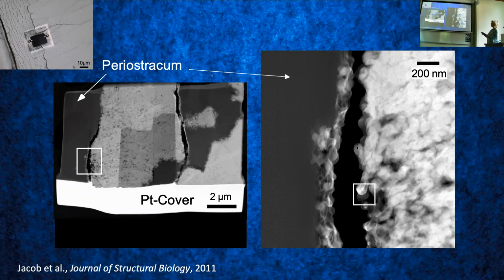So this is the foil we took out from here. This is the outer organic layer of the shell. This is the platinum cover. And you can see from the scale bar how small this foil is. That's about 15 microns by about 10 microns or so, 150 nanometers in thickness in some areas. While we were cutting, it was bending a little bit. Therefore, we ended up with a little bit of a crack here, and with some areas that are a bit thicker than other areas. That's why it's a little bit more gray.